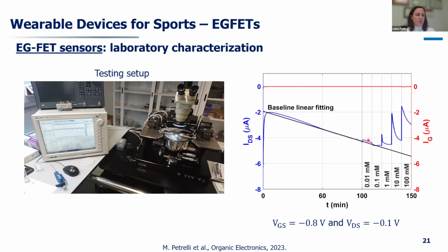And then what you see here, we do the pipetting of the different concentrations of ammonium ions. So from 0.01 millimolar to 100 millimolar, those are the levels of interest for the application we're looking at. But interesting is also to see that, being electrolyte-gated transistors, the operation voltages are very small.